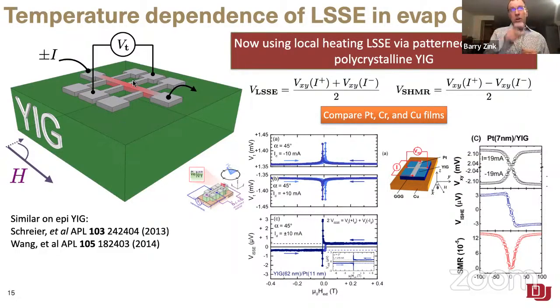So we made Hall bars of the various types of chromium, comparing them always to other materials, and you'll see that in the data in a second. But you drive a fairly large DC current through, although not enormous, through the spine of the Hall bar, and then you measure the transverse voltage, and then you pick apart what's happening and what effects are being driven by thermal effects by looking at the symmetries or the expected symmetries of the signal.